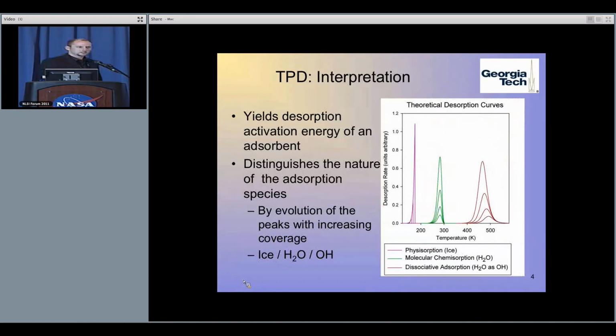Here I have some simulated data of just some very basic desorption curves, a zero, a first, and a second order. I'll tell you what that means in a second. But from these curves, we do an analysis and we can get the desorption activation energy of the adsorbent from the material. We can also, in many cases, tell whether the water that we see desorb in the quadrupole started out as ice, or molecularly chemisorbed water, which basically means that an individual water molecule finds a site on the surface that it binds to and sticks there with an energy higher than that of ice, so it'll come off at a higher temperature.